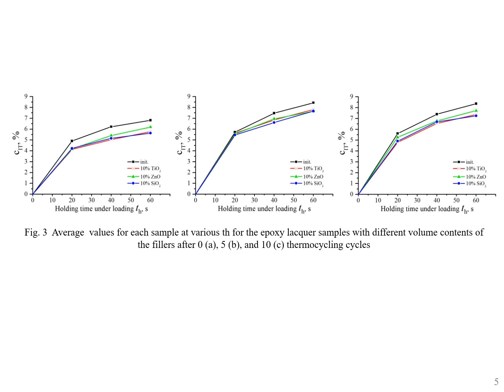The behavior of creep varying with holding time for all the tested samples is qualitatively identical after 5 and 10 cycles, with varying numerical values. For the unmodified coating, creep increases on the average by 20% after 5 thermocycling cycles for all the holding times. As the number of cycles increases to 10, the value of creep changes only slightly. The same behavior is observed for the coatings modified with zinc oxide and silicon dioxide, but creep increases within the first 5 cycles by 26% and 28% respectively. For titanium dioxide, the creep increases on the average by 35% after 5 thermocycling cycles, however, after 10 cycles, on the contrary, the creep value decreases on the average by 7% as compared to the coating after 5 cycles.